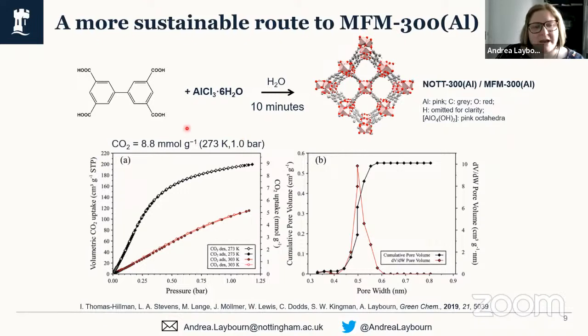And what we found when we measured the carbon dioxide uptake was that at around 273 Kelvin and 1 bar, we were able to produce a material which had an uptake of carbon dioxide of 8.8 millimoles per gram. So this was 26% higher than the conventionally prepared MFM 300 material, which is made over 3 days solvothermally and uses a piperazine modulator. We don't use the piperazine modulator to produce this material. We do get the pore widths that we would expect and that you get with the conventionally prepared material, so roughly around 0.5 nanometers for the pore widths.